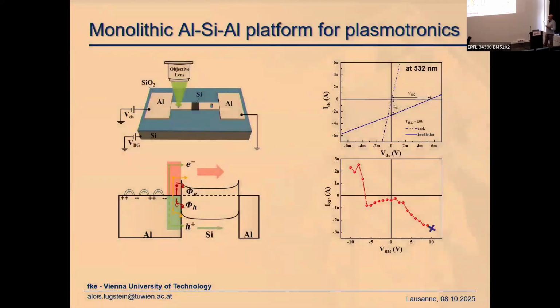Okay, so then again, Said did the following nice experiment where he made use of the backgate voltage. I mentioned at the very beginning that this aluminum silicon contact is a Schottky junction, and the Schottky junction has a particular barrier height. So it is well known that aluminum is pinned about mid-gap, so that means we have a barrier of about 600 millielectronvolts. And anyway, for the green laser, the electrons will easily surpass this barrier. So they have an energy of about 2 eV, so they can easily surpass this barrier.